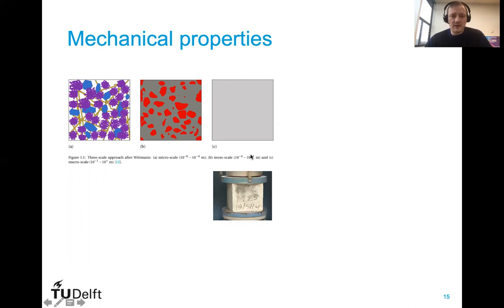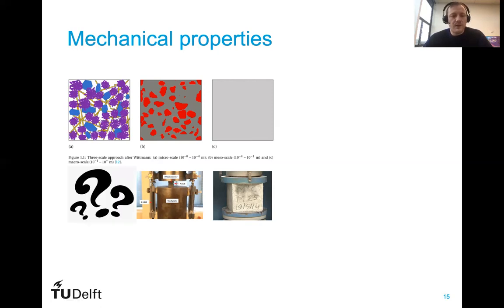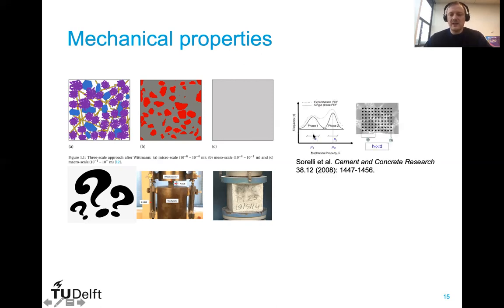And this is actually at the concrete scale where we do most of our testing. We test our compressive strength, our flexural strength, assuming that concrete has certain homogeneous properties at this scale. We can also do similar tests in a bit more difficult way at the mortar scale. So we make smaller specimens where we can still test compressive strength, tensile strength, and similar properties at the mortar scale. But what do we do at the cement hydrate scale? How do we determine properties of these individual phases at the cement hydrate scale? Well, classically in the past 20 or so years, people have been using nanoindentation, statistical nanoindentation, for example, to determine the properties of different phases in hardened cement paste.